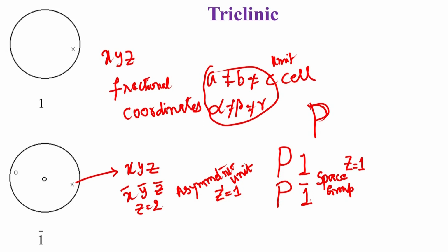That is not the correct statement, because if z is equal to 1 and it is a triclinic system, it can also be a P1 bar, in which case the molecule, atom, or the ionic species will be associated with the inversion center, what we then refer to as the special position. So, the special position in this particular case is the inversion center.